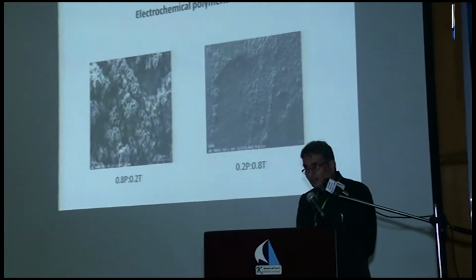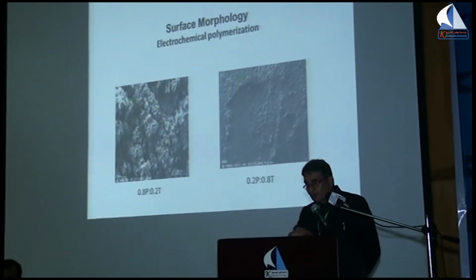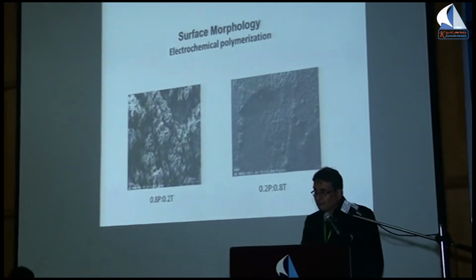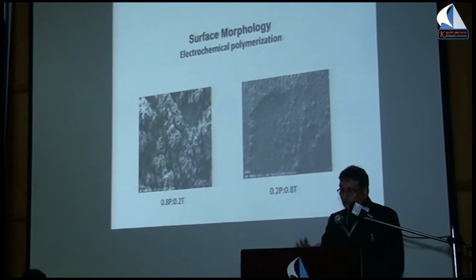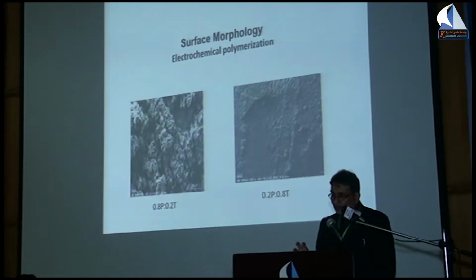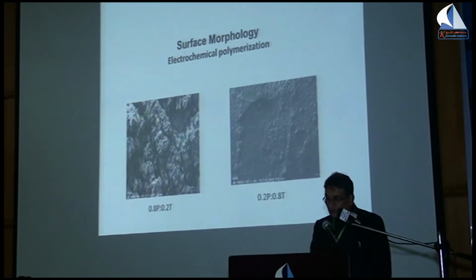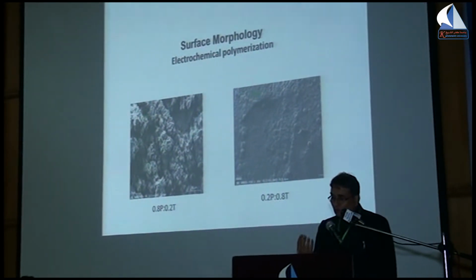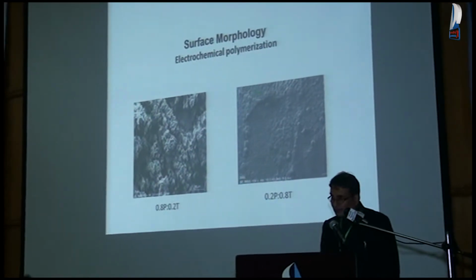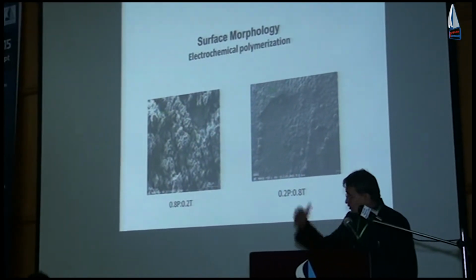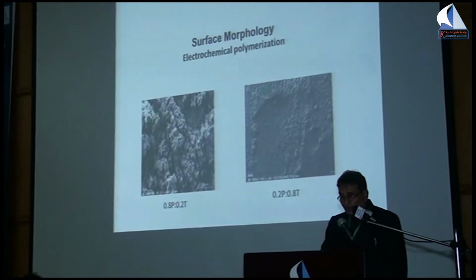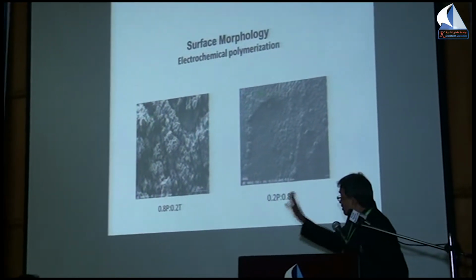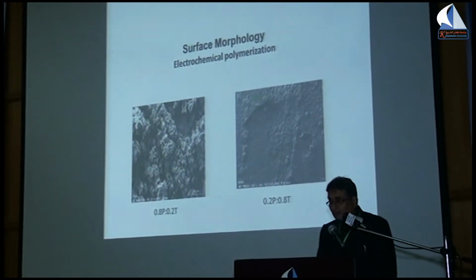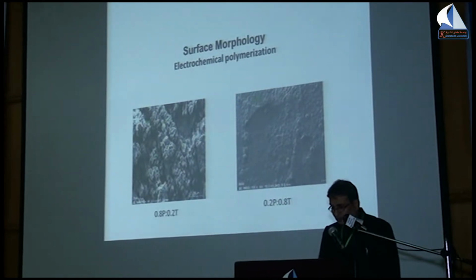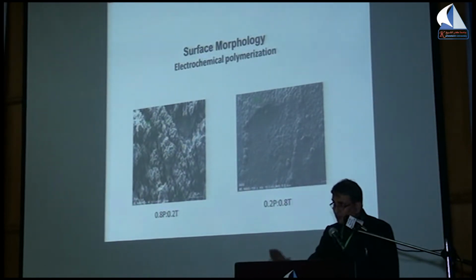Also, when we studied the surface of the materials, you can see that if the thiophene is less and pyrrole is more, you have a very globular kind of polymerization, while when the thiophene is more, you get a more planar type of surface. This is how the films get formed. So the difference is there in these two materials.